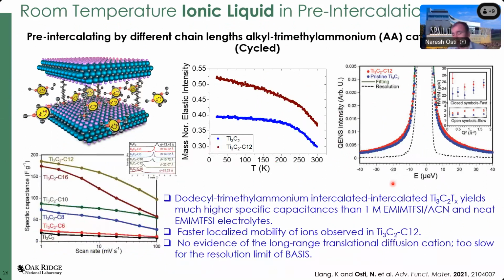Now, so far what we found is that it is very hard to get the ionic liquid in between the MXene layers. In most cases, the ionic liquids are not getting in between the layers. That's why in this particular system, before using this as an electrode, we pre-intercalated the MXene using an alkyl trimethyl ammonium cation. That means we are opening up the space between the MXene layers.